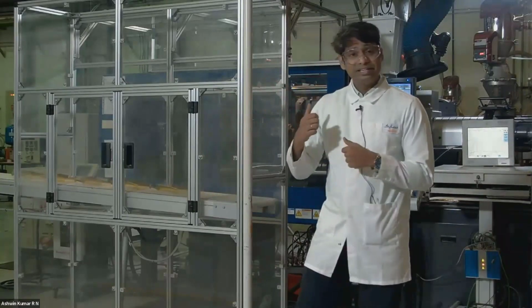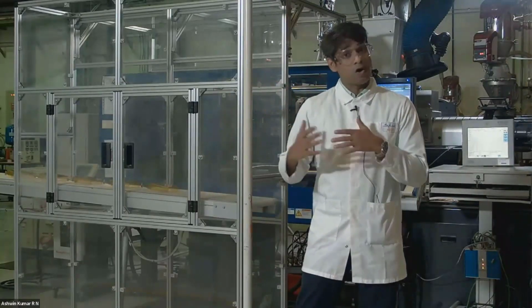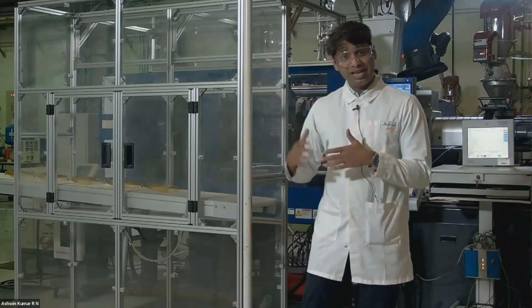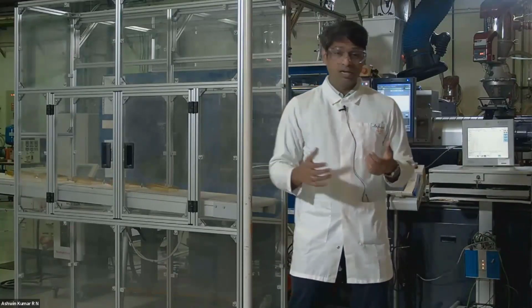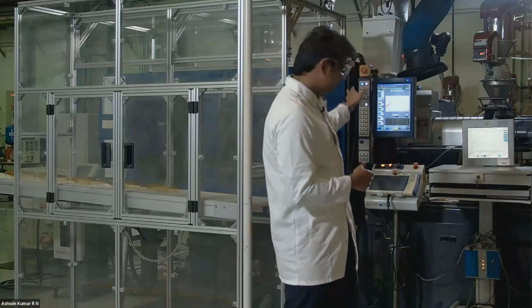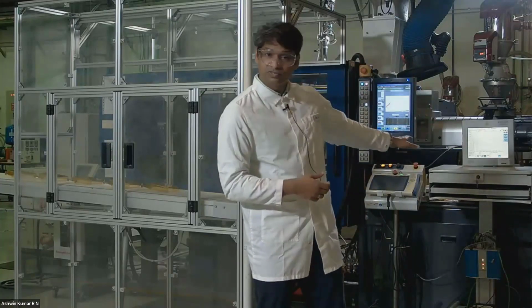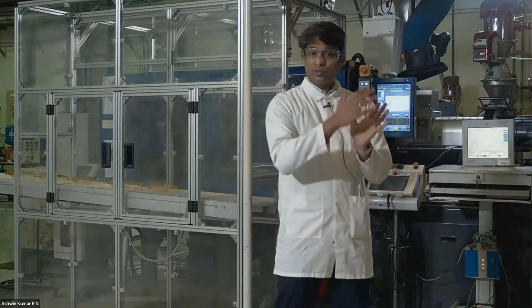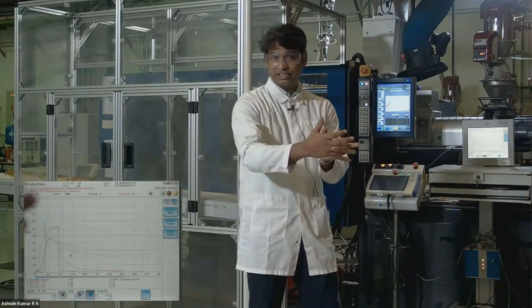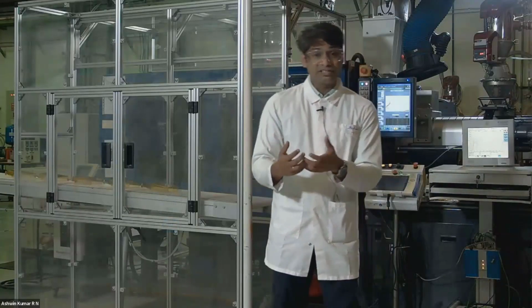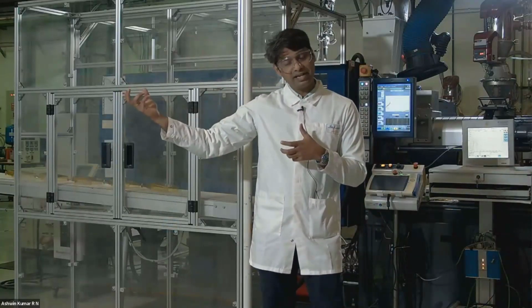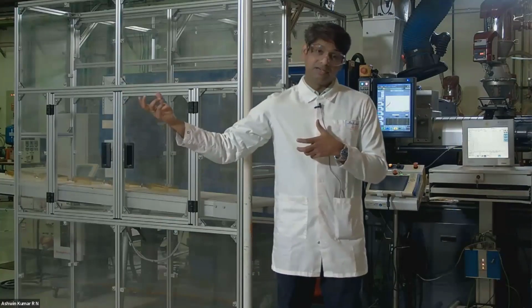So with this kind of optimization and a robust process established, we make sure that it is run for a minimum of 30 shots or about 30 minutes to ensure that the process is stabilized. All the process outputs are within a consistent range of what we're expecting. And that is where we extract the data from these molding machines, the pressure curve from the machine and the sensor curve from the Kistler acquisition unit. That data goes to the simulation to understand the correlations with the material data characterized by our experts here and the molding process used in this setup.